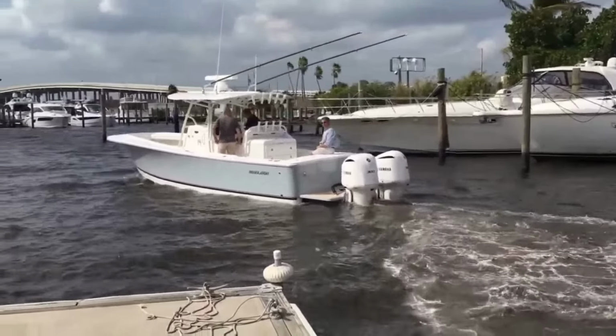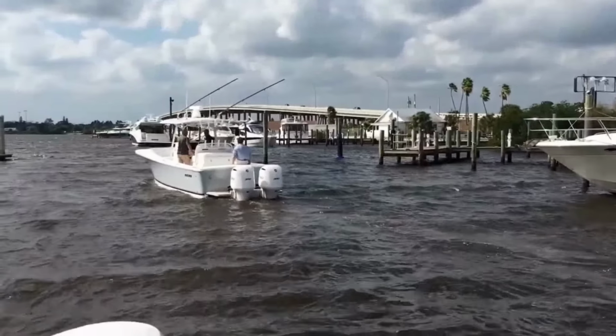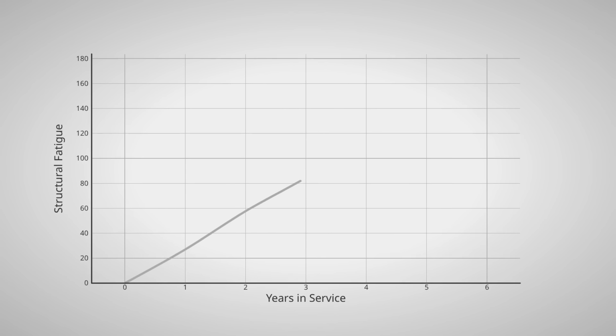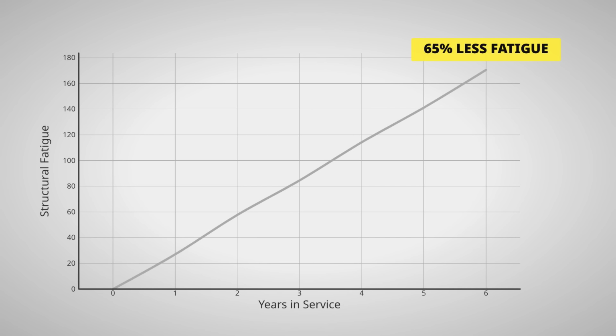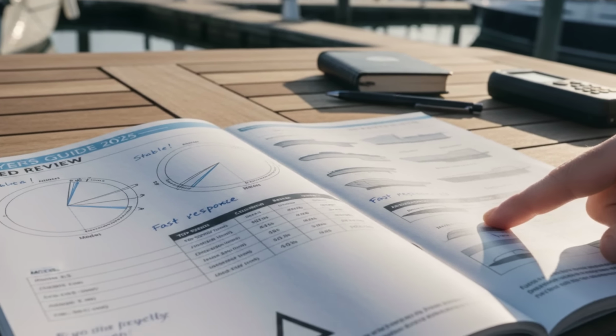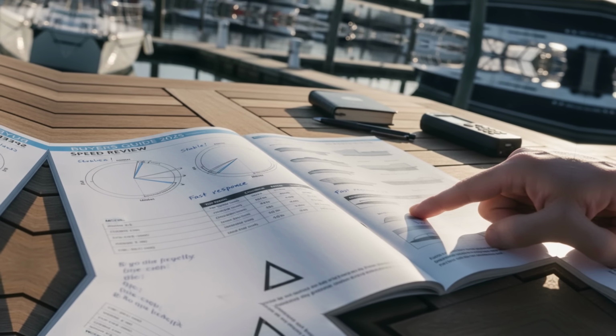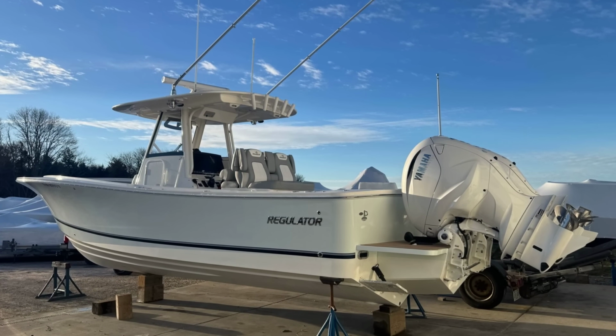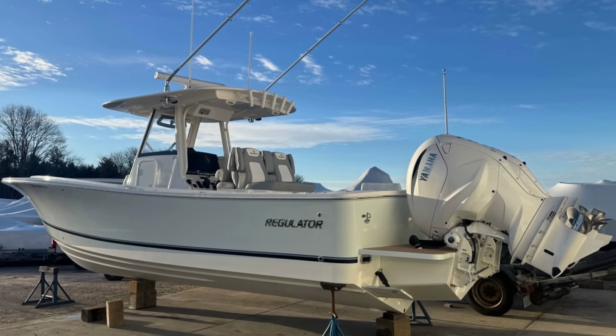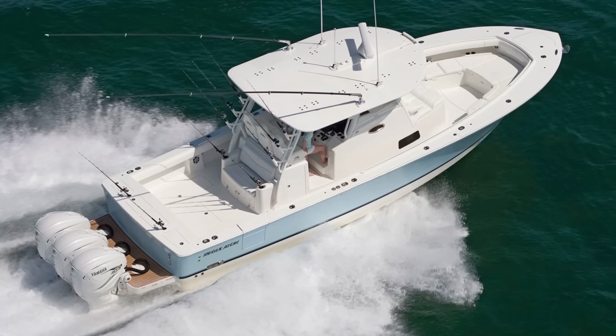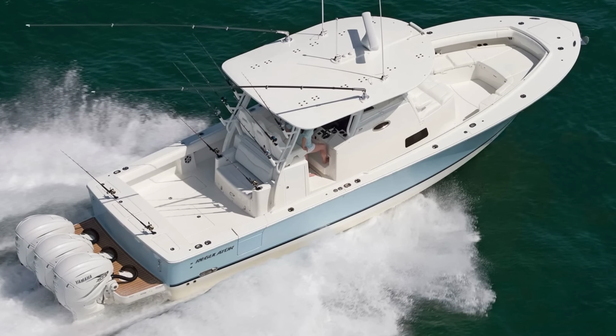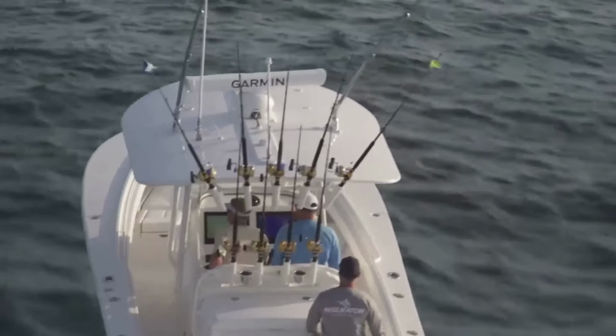That deadrise geometry keeps the bow cutting into offshore chop rather than slamming across it, and it reduces repetitive structural stress on every joint in the hull over a service life of decades. The Regulator 31 with twin 450 horsepower Yamaha outboards tops out around 65 miles per hour, confirmed in the same 2025 Buyer's Guide review. The published dry weight with engines is over 11,000 pounds. That weight is intentional. It creates the low center of gravity that keeps this hull composed at 20 knots in conditions that have other boats slowing to a crawl.